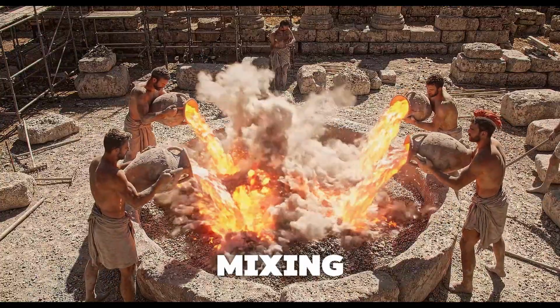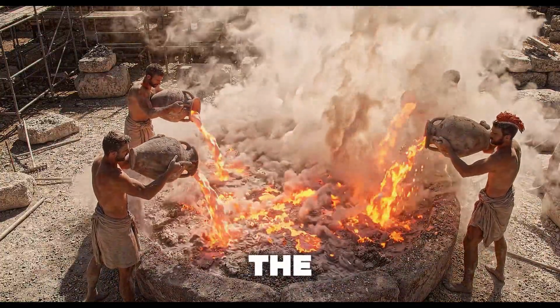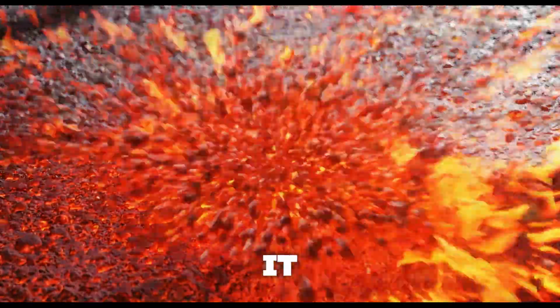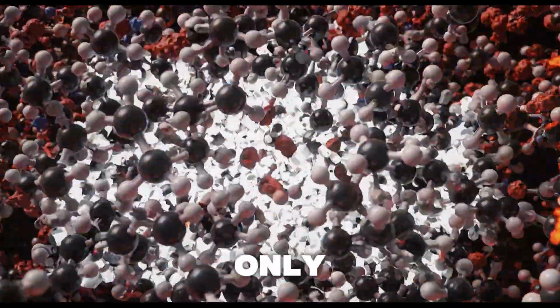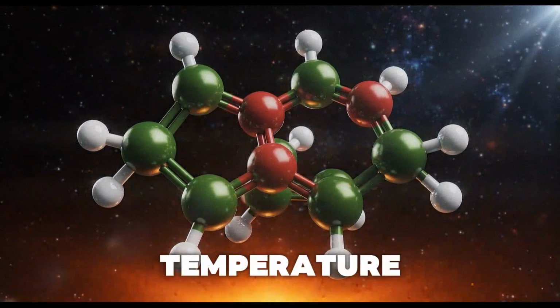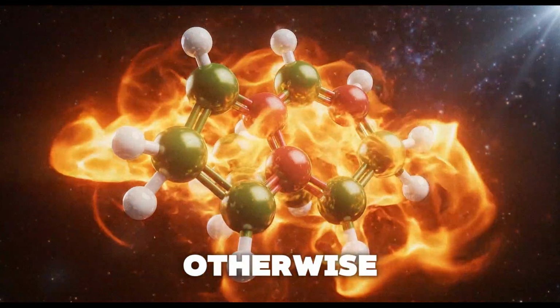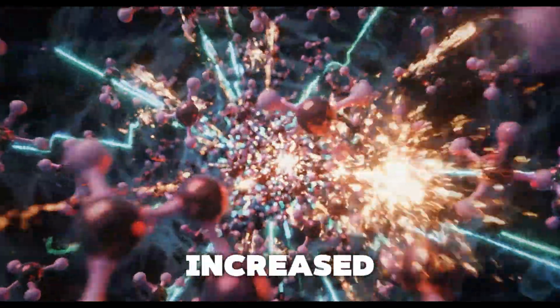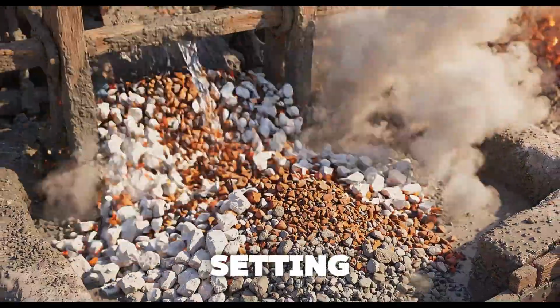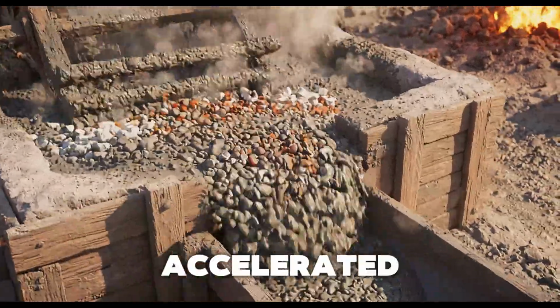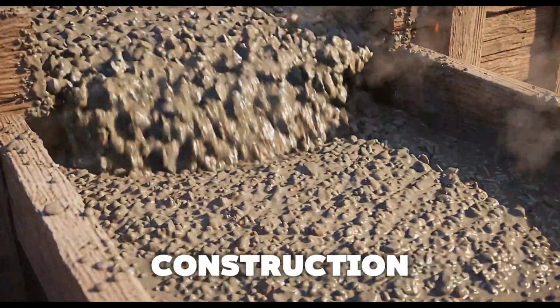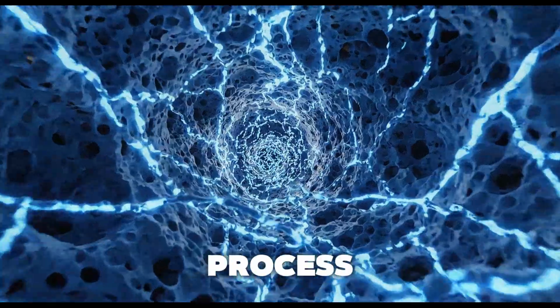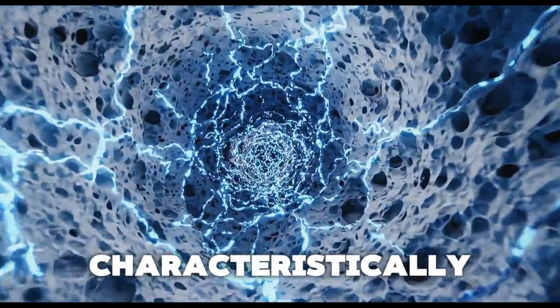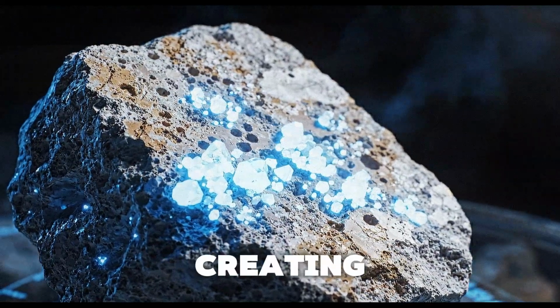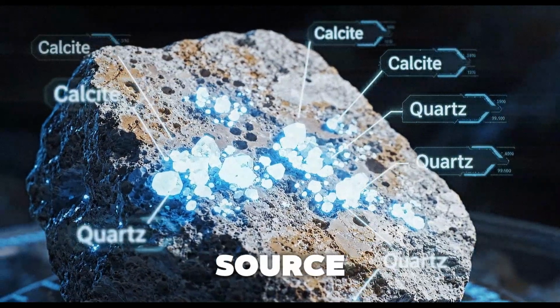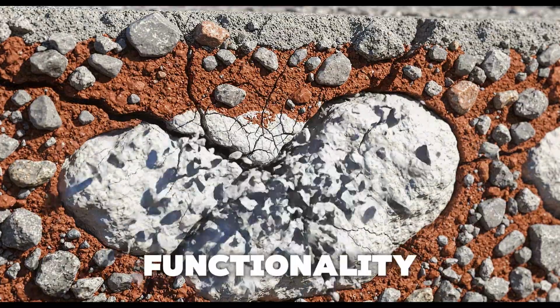The benefits of hot mixing are twofold. First, when the overall concrete is heated to high temperatures, it allows chemistries that are not possible if you only used slaked lime, producing high-temperature associated compounds that would not otherwise form. Second, this increased temperature significantly reduces curing and setting times, since all the reactions are accelerated, allowing for much faster construction. During the hot mixing process, the limeclasts develop a characteristically brittle nanoparticulate architecture, creating an easily fractured and reactive calcium source, which could provide a critical self-healing functionality.